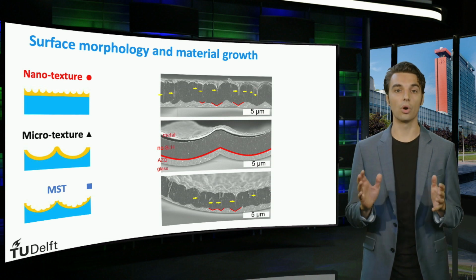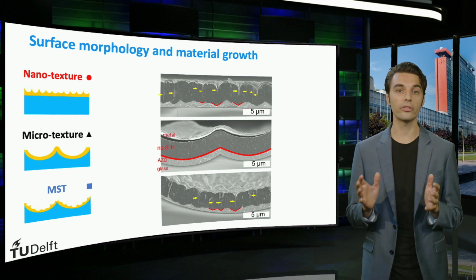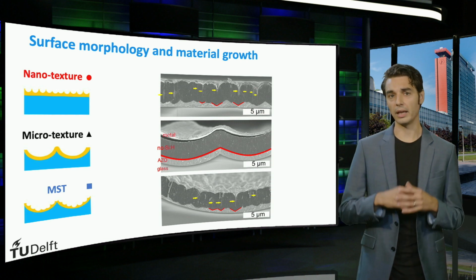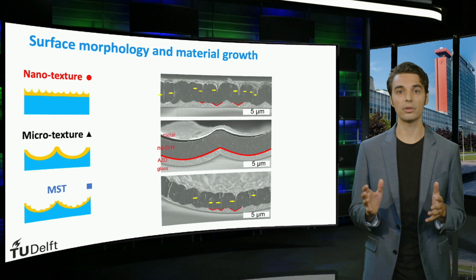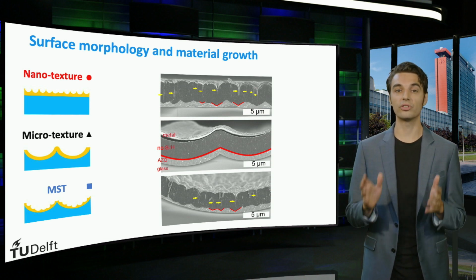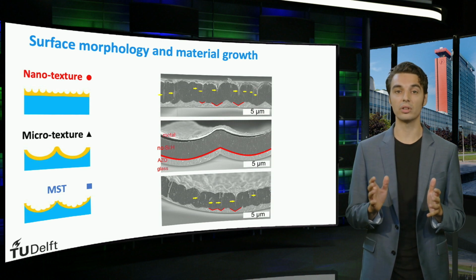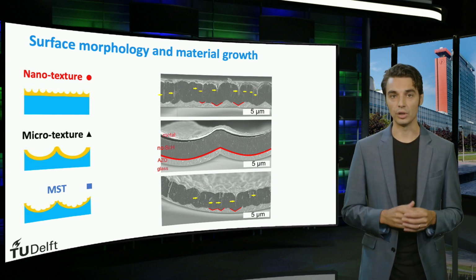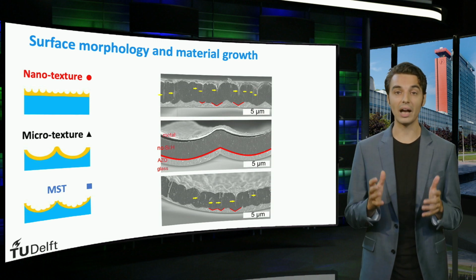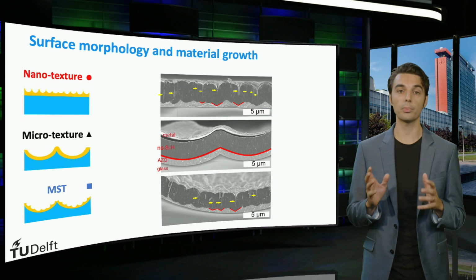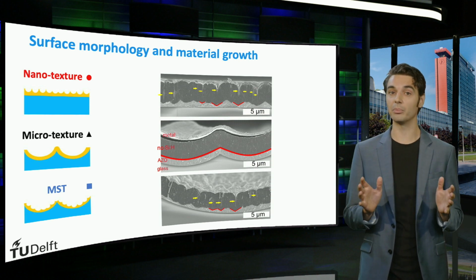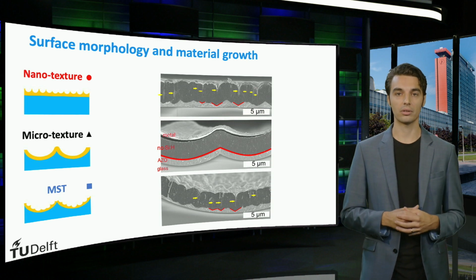The cracks are zones of porous material that create shunting paths and strongly increase charge carrier recombination. The increased recombination and leakage current result in lower VOC and fill factor. The solar cell performance is directly related to the density of these defective filaments. Note that while here the results are shown for nanocrystalline silicon, achieving a device quality crack-free material on substrates with sharp features is generally very challenging for any PV material that contains a crystalline phase.